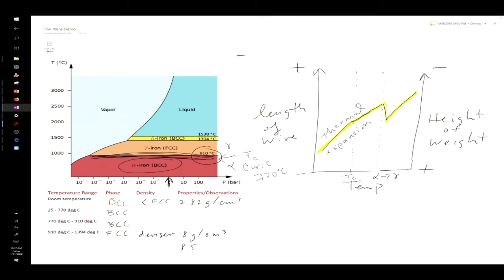Did you say that it lost its magnetism once the unit cell switched from BCC to FCC? So the question was, did I say that the wire lost its magnetism once the material went from BCC to FCC? No. The loss of ferromagnetism to paramagnetism occurred at 770 degrees Celsius for this material. The phase transformation from BCC to FCC occurs at 910. So they are related, but in this case, it doesn't have to be at the same temperature. Your magnetic transition can be at a different temperature than your phase transition, because it all has to do with the spin of your iron centers itself.